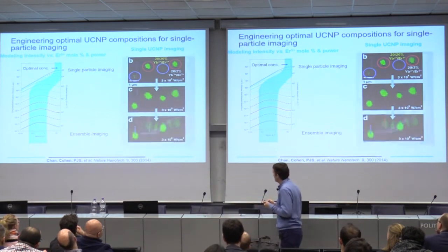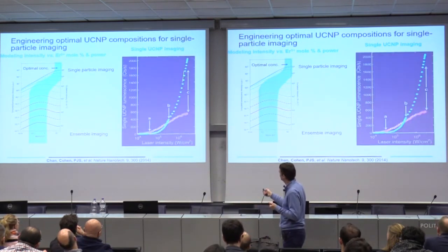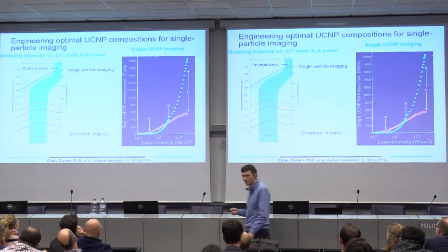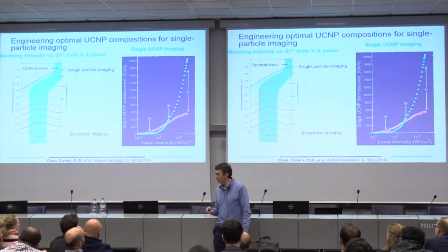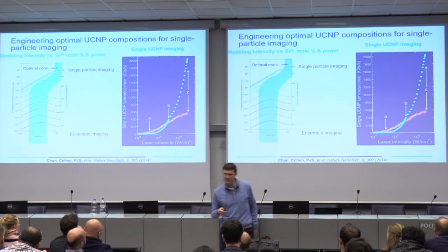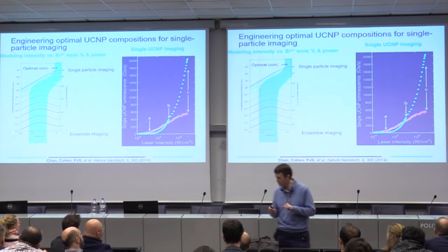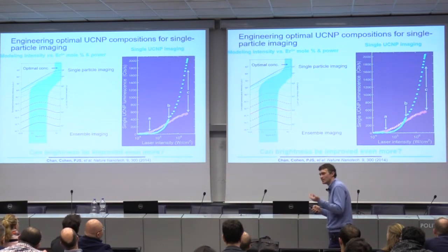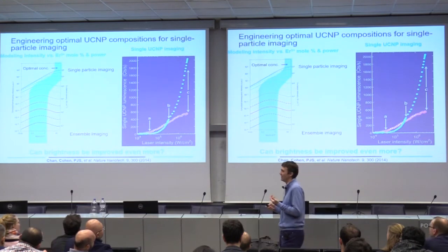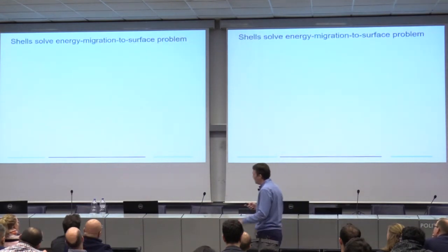And what we saw is that these particles got a lot brighter, as you can see here. So this got us pretty excited. We're now getting kind of 1 to 2 orders of magnitude more signal out of these particles. So that was the first thing that sort of changed. Of course, we did ask the question, well, that's great, but can they be brighter? Can we make them even brighter?